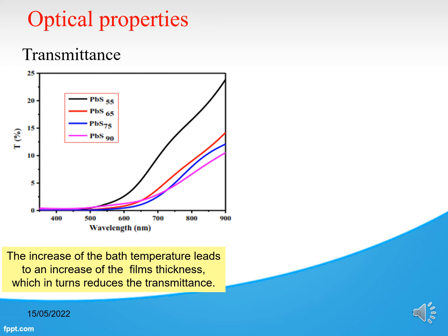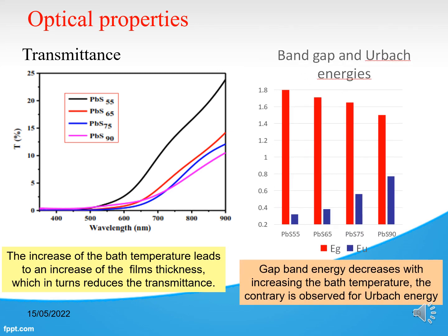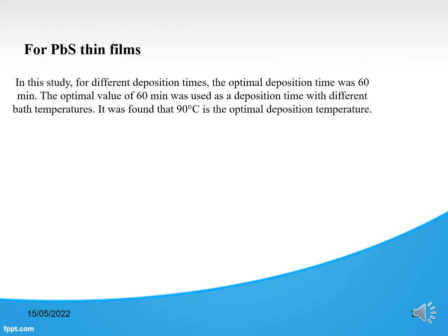Optical properties. Transmittance. The increase of bath temperature leads to an increase of the film thickness, which in turn reduces the transmittance. The band gap and the Urbach energy. Band gap energy decreases with increasing the bath temperature. The contrary is observed for Urbach energy.